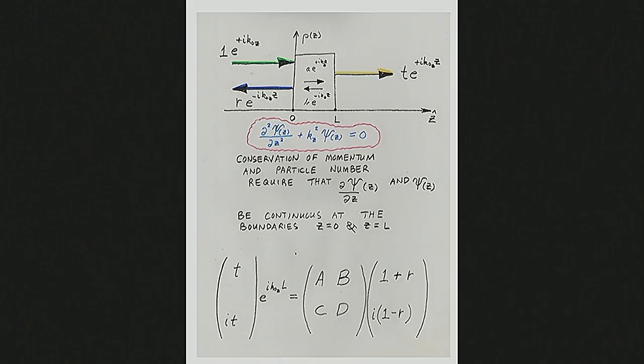So the way to solve that is you just take a step backward and not make that Born approximation, and you solve the Schrodinger equation exactly. And for this one-dimensional specular case, it turns out it's possible to do this with very high accuracy and precision. So again, I've illustrated beam in, beam reflected, beam transmitted from this potential along Z in this simple cartoon representation, because remember, the specular problem that we're talking about is in fact just one-dimensional. So the only thing that counts is the function Z, that spatial coordinate.